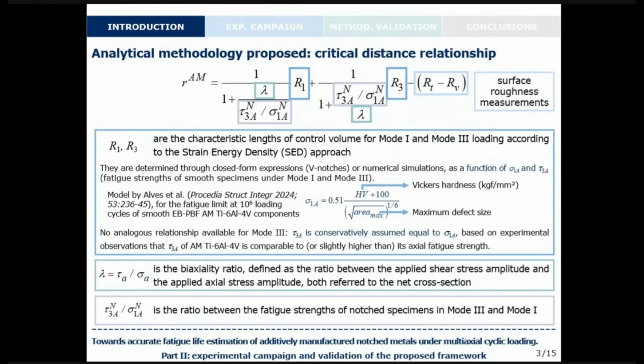Then, since we didn't find any analogous relationship in the literature for the Mode 3 values, tau 3a is conservatively assumed equal to the corresponding value of sigma 1a, based on the experimental observation that, at least for additive manufacturing Ti6Al4V specimens, tau 3a is comparable to or even slightly higher than its axial fatigue strength. Then, R_AM, as you already saw, is a function of the biaxiality ratio, tau_a over sigma_a, of the ratio between the fatigue strength of notched specimens in Mode 3 and Mode 1 loading, and of some surface roughness measurements.